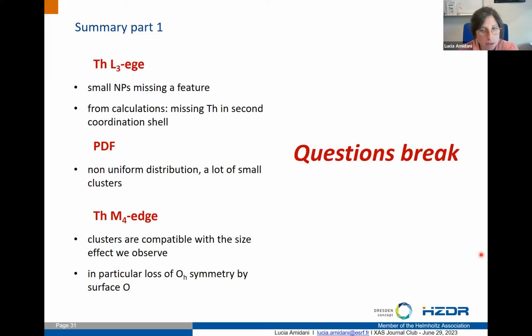And regarding the termination, at the beginning of the L3 edge I specified it was a tentative evaluation of the surface as bare, missing scatterers. So in fact, I'm not terminating the surface. And of course, this limits what I can say. For example, this is why I'm not analyzing the effects on the white line, which would need a better description of the structure.